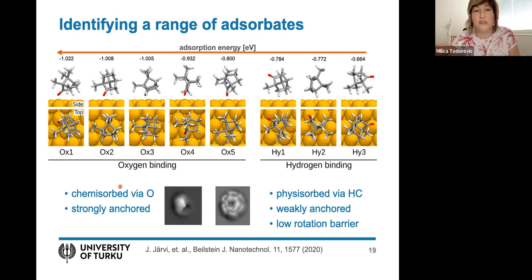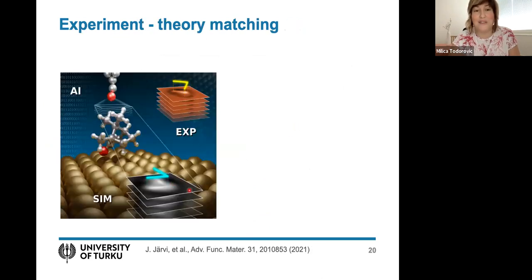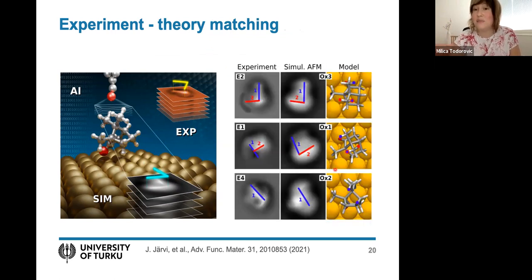But in order to really determine what was behind, we had to do some simulated AFM on each one of these molecules. We had to simulate a stack of images to imitate the tip approaching the surface. And then we compared it to the stack of images obtained from exactly the same experiments. And this was the result. So here are the three best matches between the simulated AFM in the middle column and the experiment on the left. And you can see the simulated AFM is just as blurry and indistinguishable as the experiment. But if you do some analysis, you can see that there are some bright features, and we could analyze their length and orientation and compare them to experiments. And this is how we found the best matches.